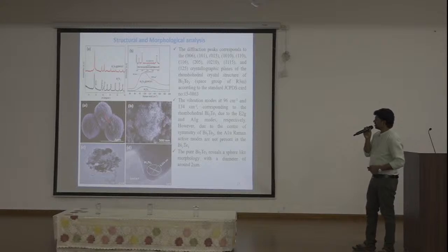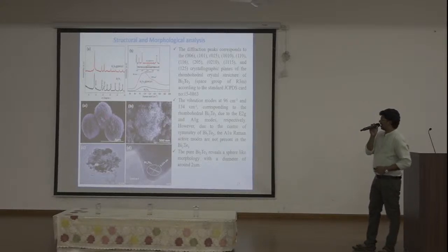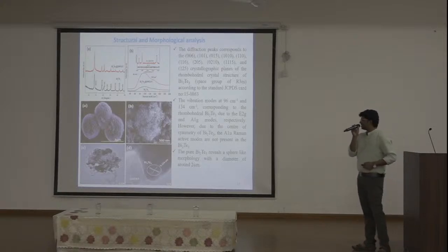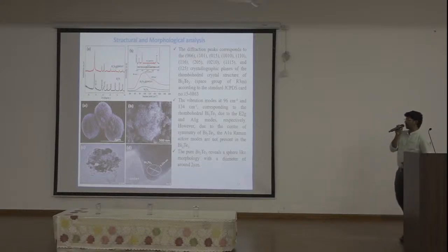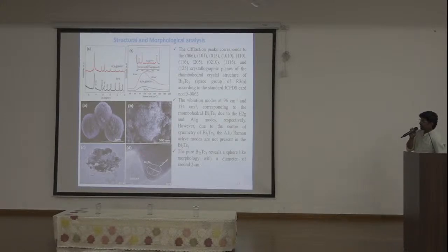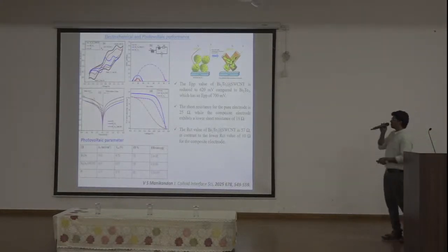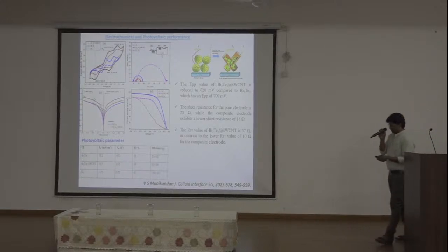And the pristine bismuth telluride has a sphere-like structure after hydrothermal conditions. It is affected by the growth condition, but the sheets are more attached in the CNT composition. We can see the CNT along with bismuth telluride sheets grown on and attached to the functionalized CNT. So this provides more active sites to improve the electrocatalytic activities. We can see more in the electrochemical behavior. This work was also recently published in the Journal of Colloid and Interface Science.